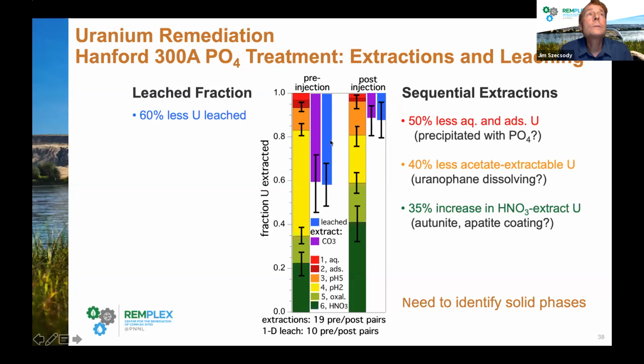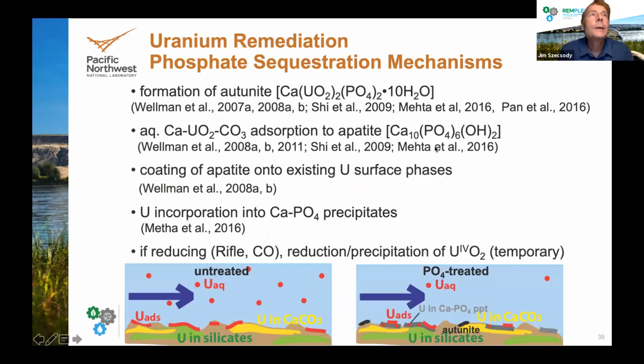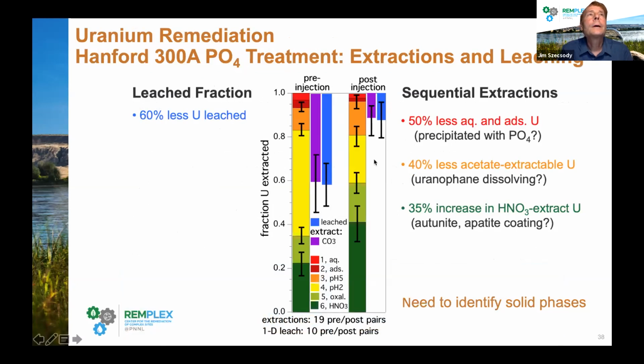Now, to compare those leach experiments to the extractions, which are these stacked bars, the aqueous and adsorbed uranium, you can see here, is smaller after phosphate treatment. The high solubility phases are also smaller, and the low solubility phases are larger because of treatment. Now, this is the limitation of the extractions. We think that the high solubility phases probably mean that there was uranophane dissolving, and the increase in low solubility phases, we're forming autunite or an apatite coating on uranium phases, but we really need to identify what those solid phases are. So that goes beyond this screening shown here.